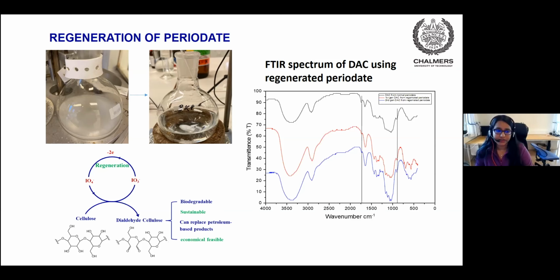So I have used sodium hypochlorite here. When sodium hypochlorite is mixed with the spent periodate water from the industry in a specific amount and at a specific pH, it reacts to form an insoluble precipitate of sodium paraperiodate. When this is dissolved in a suitable acid, it forms the solution back, that is, sodium periodate in solution, which can be used again to oxidize the cellulose to dialdehyde cellulose.